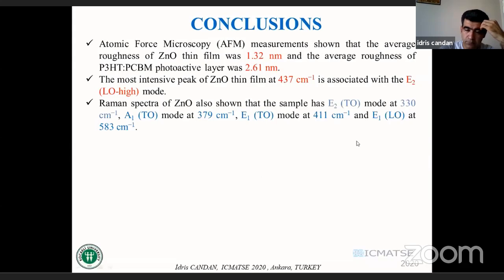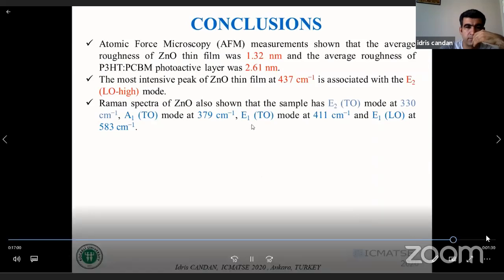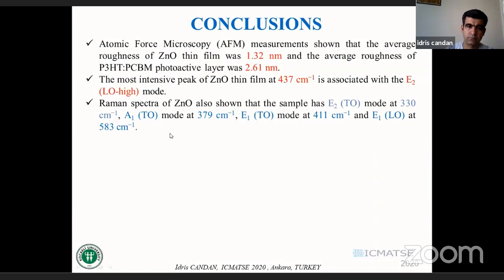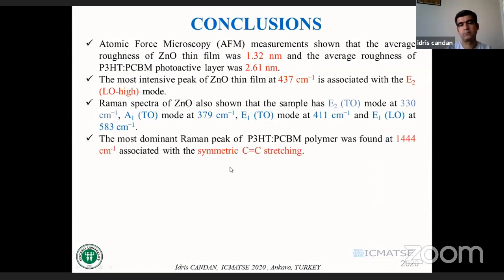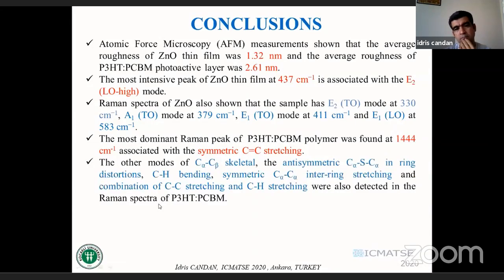that the sample has E2 mode at 330 and A1 TO mode at 379 and E1 TO mode at 411 and E1 LO at 583 centimeter to the power of -1. The most dominant peak of the P3HT:PCBM polymer was found at 1444, associated with the symmetric carbon-carbon stretching, and the other modes, carbon alpha, carbon beta stretching, and antisymmetric C alpha-S-C alpha in ring distortion, CH bending, symmetric C alpha inter-ring stretching, and combination of CC stretching and CH stretching were also detected in the Raman spectra of P3HT:PCBM.